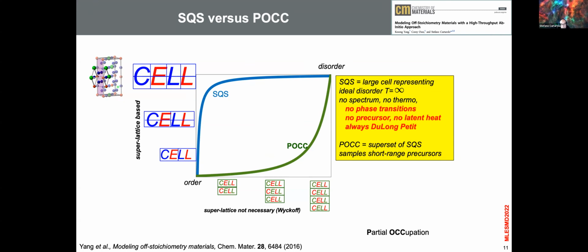But if you take the spectrum of these structures and you bring them to zero temperature, you will never have any phase transition. Why? Because they all represent ideal disorder. So if you have a linear combination of ideal disorder, you get ideal disorder. There's nothing you can do. That's why we stopped using SQS and we generated POCC, which, look here, are small cells, but they are shuffled around. Yes, we suffer a little bit because we cannot really reproduce long range interactions, but they do reproduce latent heat and they allow us to get phase transitions. That's the trick of our system.